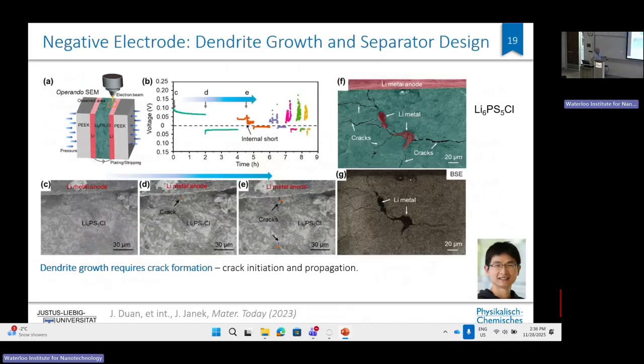One comment is that if you have a stable electrolyte and a stable separator, and you plate lithium, the belief that they are stable against dendrites is, of course, also a misbelief. You see here a sulfide separator, an argyrodite separator. The lithium metal easily went into the separator. There was lithium metal plating, and maybe a nucleus then cracked the separator here at the top, and then simply grew into the solid electrolyte. So still today, I think dendrite growth, even with solid electrolytes, is being considered as an issue. Not only because you have a stone as a separator will it be stable towards lithium growth, because all these materials, of course, are polycrystalline. They have grain boundaries that may have different transport properties, may have different electronic properties, and it's a very complicated story that enters into that.